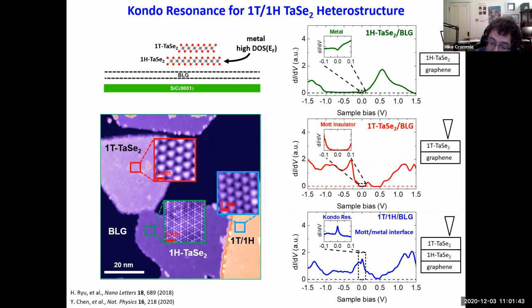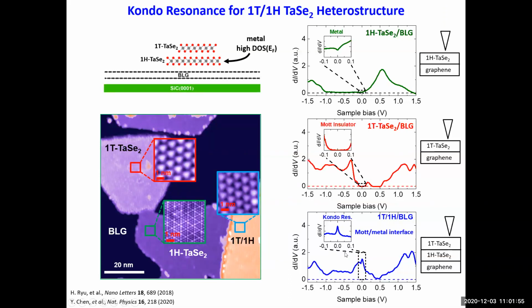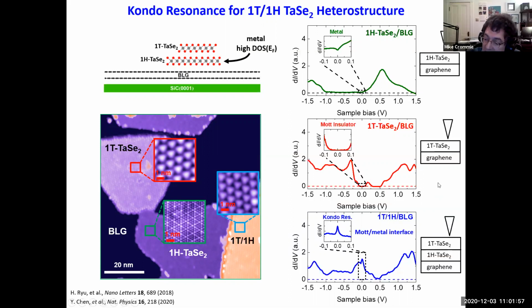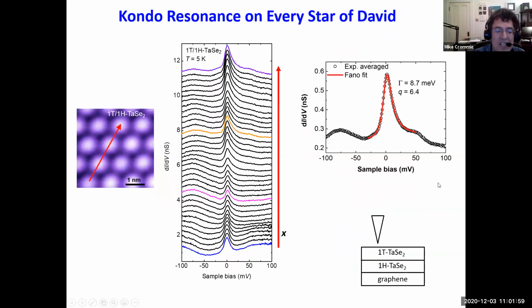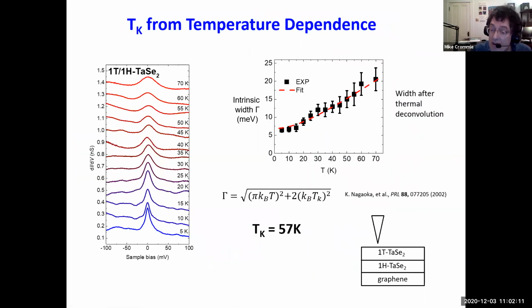But if you zoom in and do some STM spectroscopy, then the electronic structure is completely different from either of the ones I just told you about, because we see a sharp, narrow resonance at zero, at the Fermi level. And here you can zoom in, you can see that, and we believe that that's a Kondo resonance. And this Kondo resonance we see all over the surface on every Star of David.